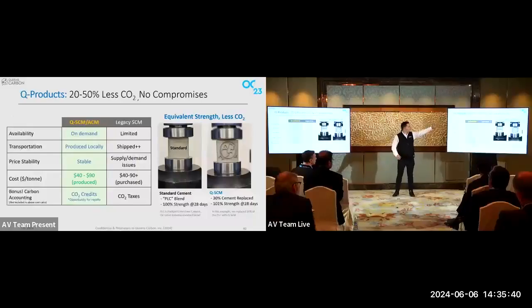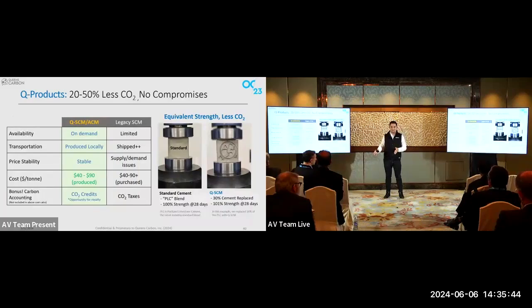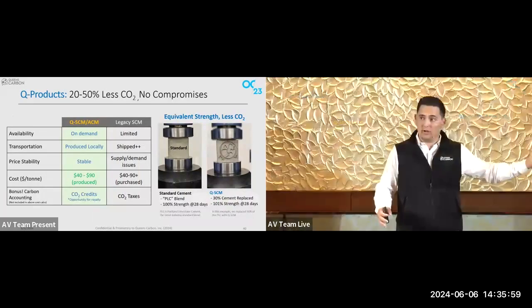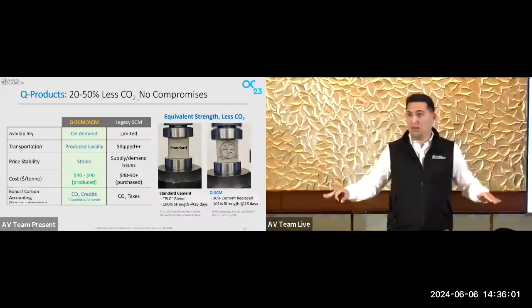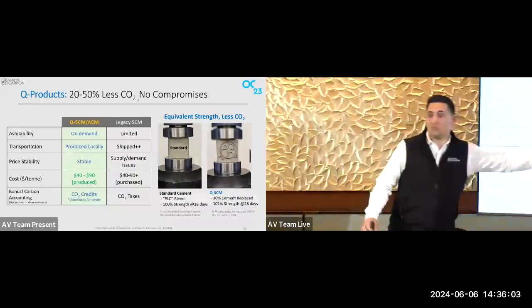So the header of this slide is really what this is about. We want to have no compromises on the journey to decarbonization. Today, we're excited to say we could do 20 to 50% less clinker, which means 20 to 50% less CO2, and we want no compromise. We don't want to blow up the energy stack. We don't want to have 6 gigajoules or 8 gigajoules per ton of energy. We believe our process is 2 to 3 gigajoules per ton, and that's due to that low temperature aspect. And of course, the cost will follow.